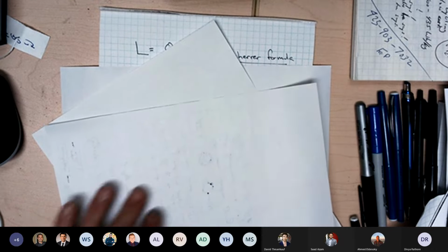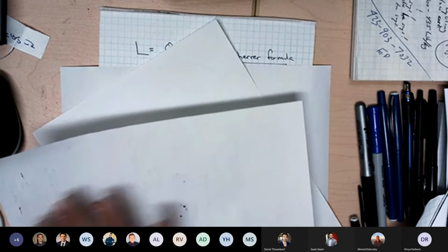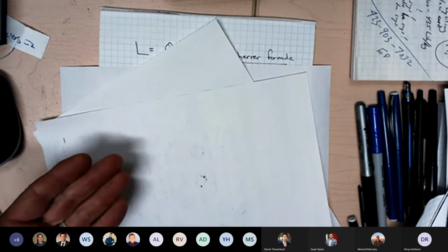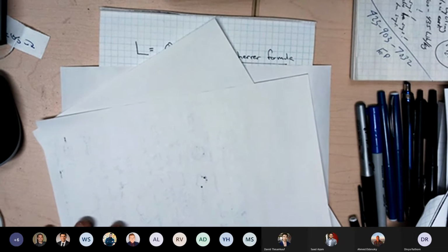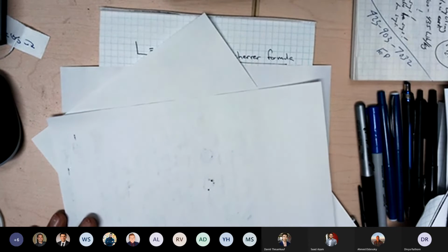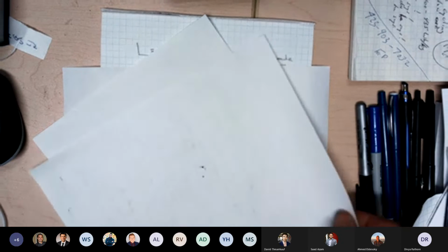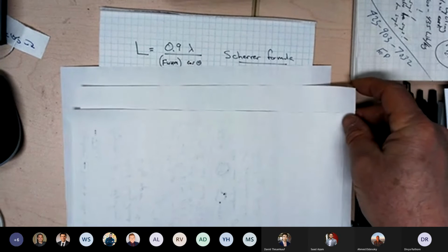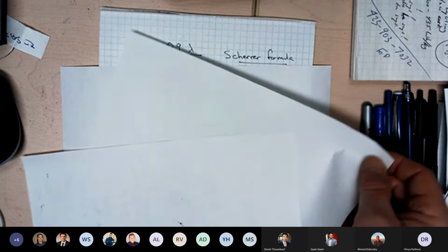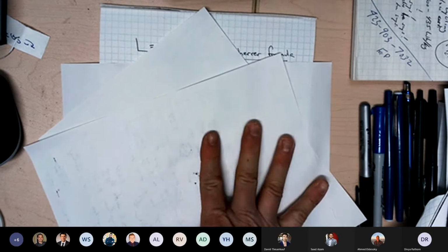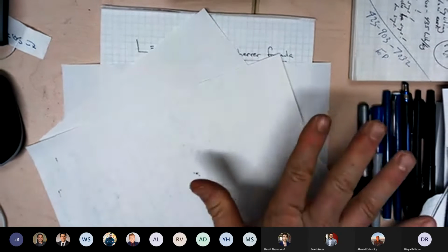The reason is there's good order in two dimensions along the graphene sheet. They're stacked parallel, so that means you get the diffraction peak from the parallel stacking, but there are no 3-dimensional correlations at all because the layers aren't organized in a stacked AB fashion, the way they're supposed to be. So you can tell when you see this triangular peak with a very sharp, steep left edge that you've got big sheets and full turbostratic misalignment like that.